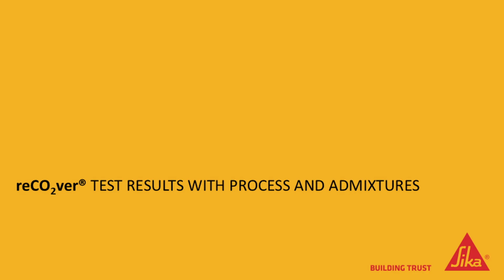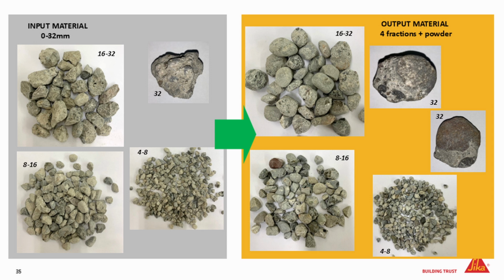But what did we get? I want to show you some results of that. Some pictures to see. On the left side, in the gray area, you see the input material, and for better comparison, we sieved it. Maybe you see it best with the 16-32 coarse material. On the left side you have a lot of cementitious material around the aggregates, and on the right side you see the material as it comes out of the process. Of course we want to have the lowest water absorption. That is the target.